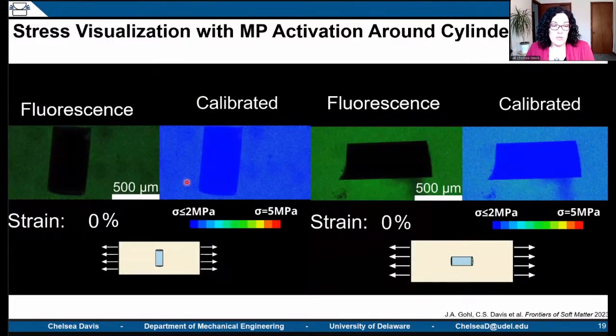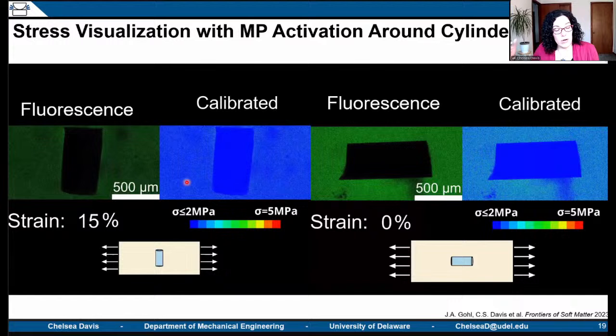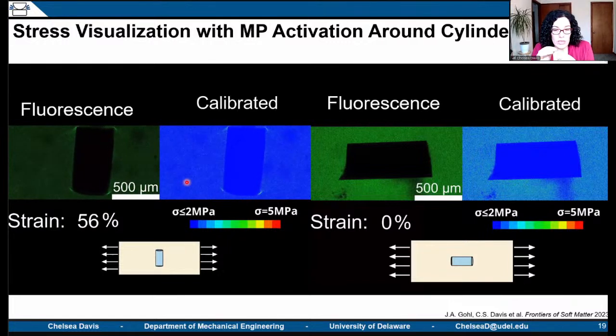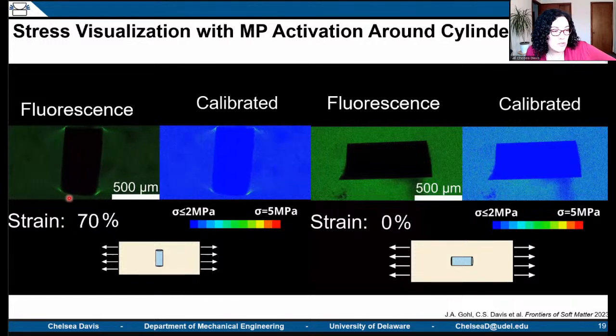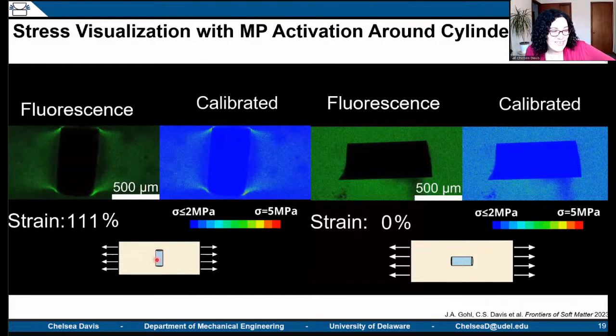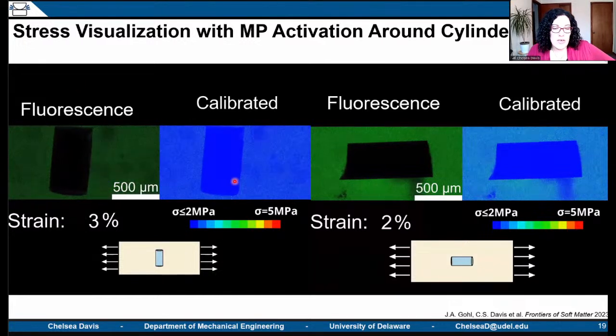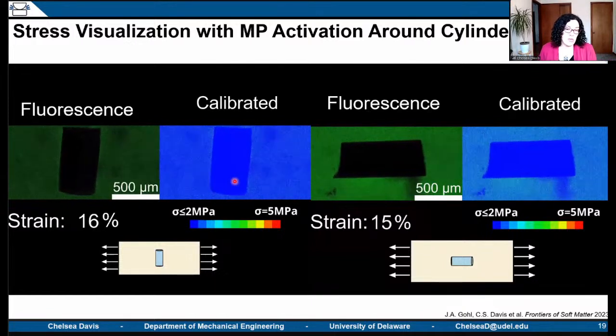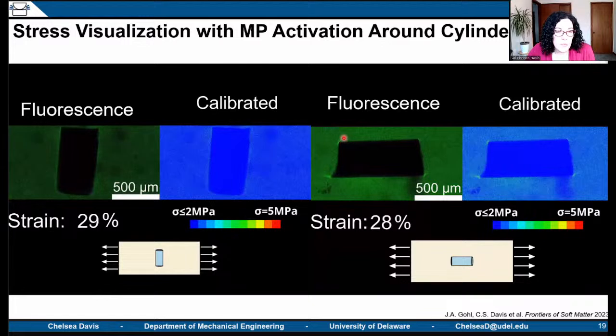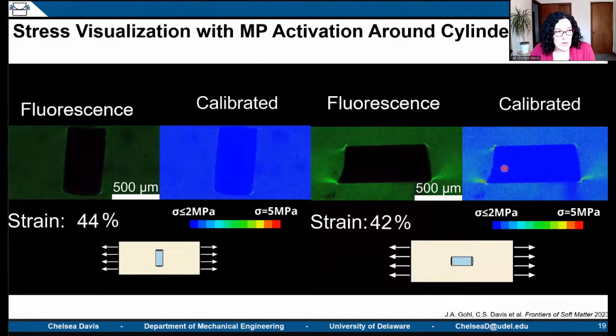And we can go further. We can start to look at stress concentrations around corners, which we've all studied in sophomore, well, what the mechanical engineers of us have studied in our sophomore mechanics and solids courses, where corners or really sharp radii of curvature features tend to concentrate stresses. And that's what we observe if we put a sharp shard of fiberglass or glass fiber into our system, either orthogonal to the stretching direction or parallel to the stretching direction. In either case, around these sharp corners is where we see all of the stress concentrating.